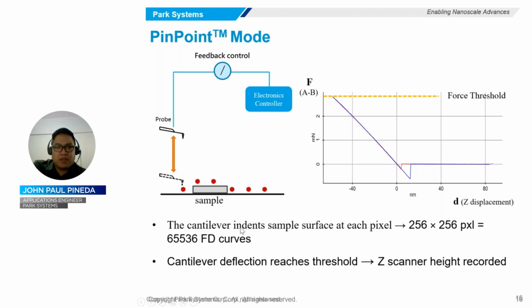So in brief, an AFM probe approaches and indents the sample surface at each pixel within the area to be imaged. For example, if the cantilever indents the surface at 256 by 256 pixels, we will expect about 65,000 force distance curves generated to map the sample mechanical properties. Once the cantilever deflection reaches the force threshold, the Z scanner height is recorded, and reconstruction of this will give the topography information of the sample.